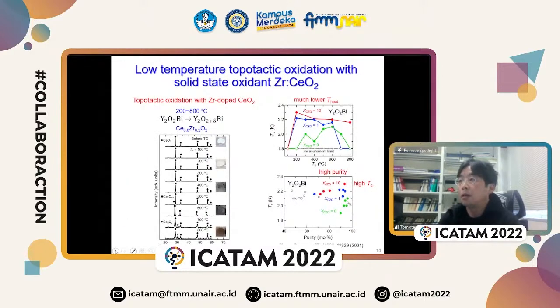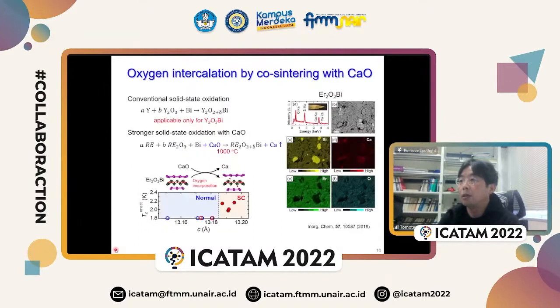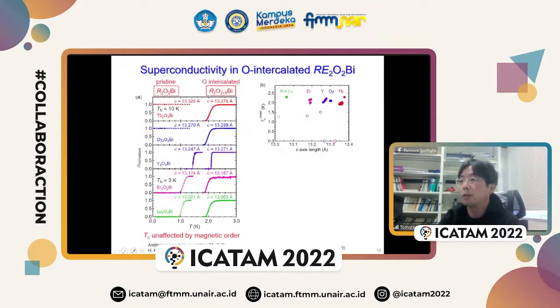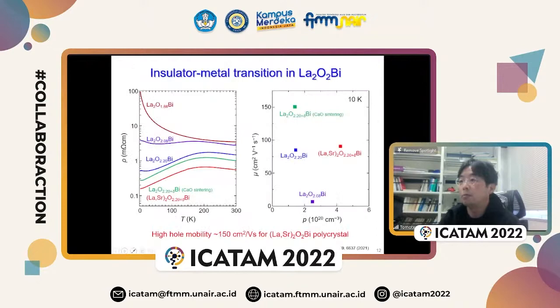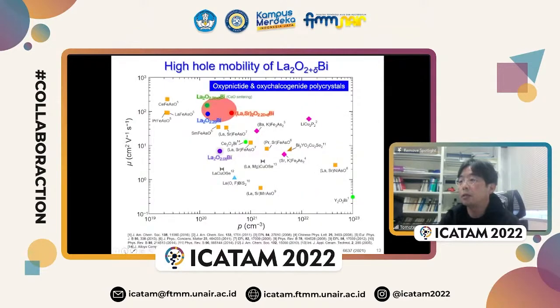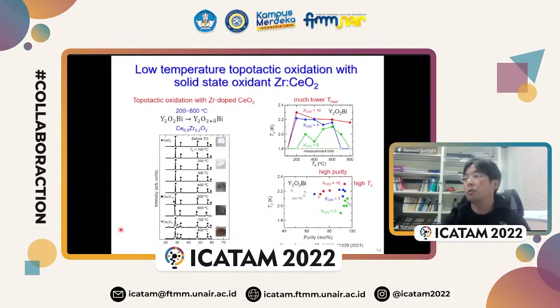And previously we performed the oxygen intercalation by using high temperature, such as 1000 degrees or so. This high-temperature sintering often resulted in the formation of impurity phases. So we were looking for a more efficient oxygen intercalation method at lower temperature. This is one of the low-temperature topochemical oxidation methods.